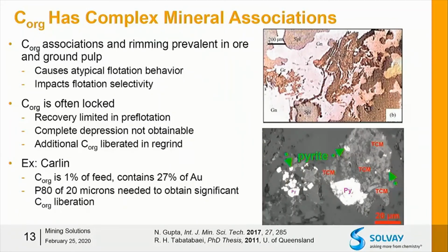and it's either because it's associated with carbon, or you can actually see carbon rimming, where you find basically a coating of carbon on the surface of either a value mineral or a gangue mineral. And you can really see this from some of the micrographs that I presented here that are out in the literature. On the top right, you see carbon is a dark-colored material, galena is light-colored, and sphalerite is gray in this carbonaceous polymetallic ore. That scale bar is 200 microns if you can't read it. So you can see association between carbon and your value minerals at a size that is much, much finer than you would actually liberate in any standard grind.